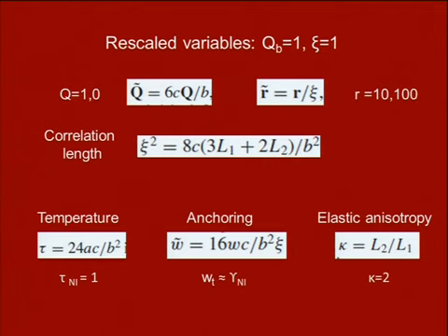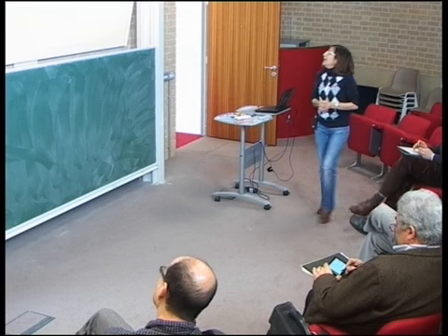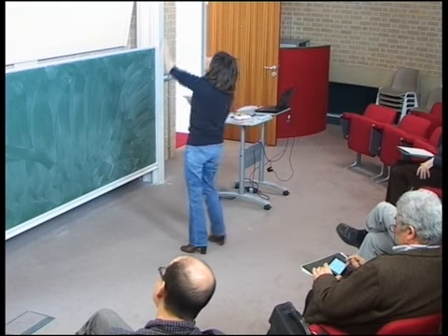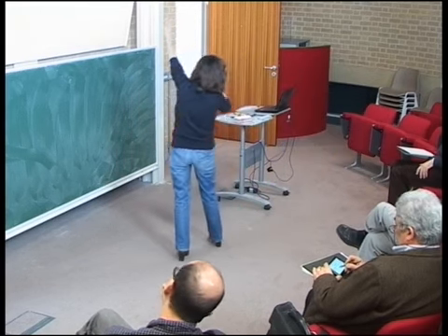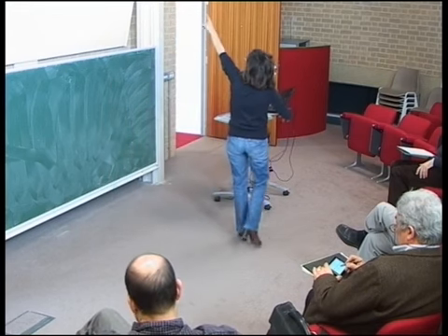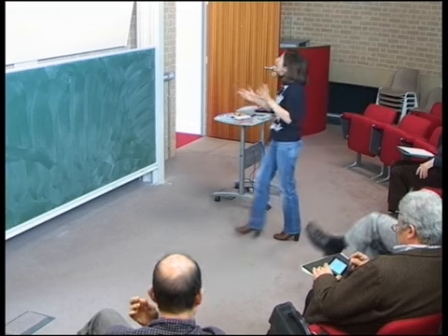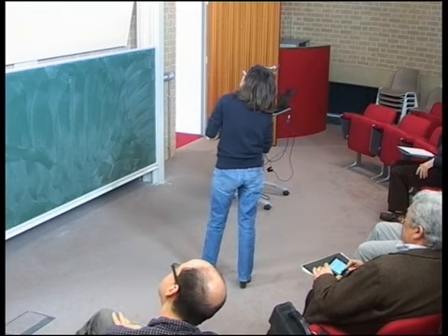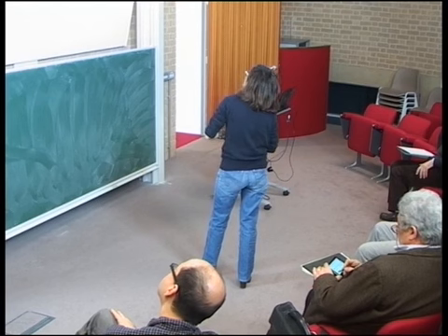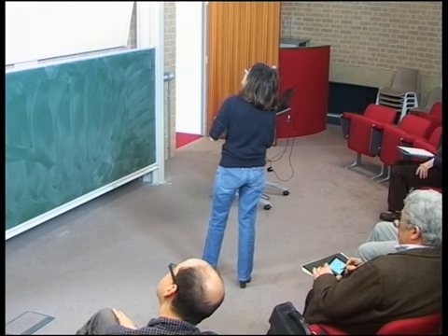And I also rescale my space in terms of the bulk correlation length, which, if I'm near the nematic isotropic transition, can be large, because the transition is weakly first order. So I'm looking at systems where there is structure, surfaces later on, that varies between 10 and 100 correlation lengths. I don't like to go below 10 because Landau should not work if you're well below the correlation length. You have to be bigger than the correlation length.